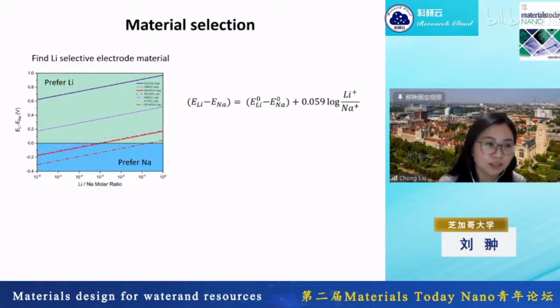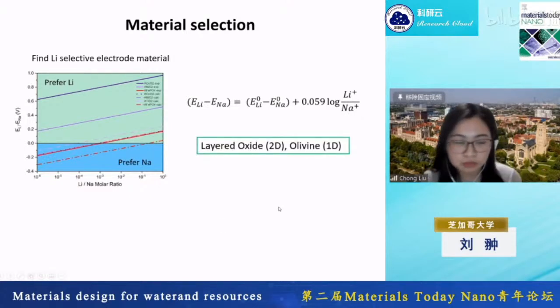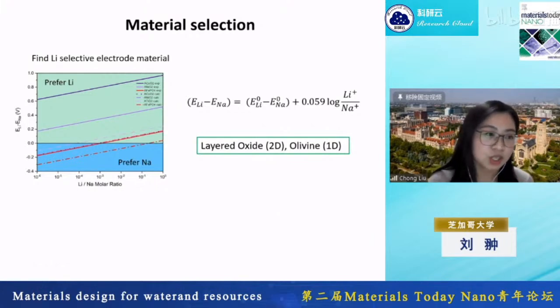So this is a rich database because of the gigantic amount of work done by the battery field. So you can look at different kinds or categories of material, and you look at the lithium intercalation potential and sodium intercalation potential in their pure phase. And the higher the difference would allow you to compensate more of the concentration difference. So you want a big difference in their intercalation potential. By looking at that, we determined we will work on the 1D olivine structure and 2D layered oxide material.